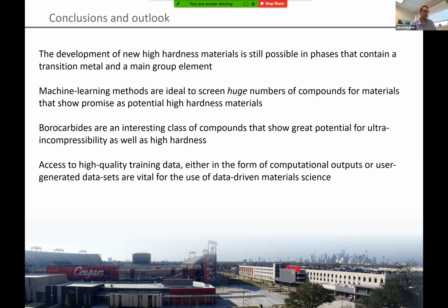Yeah, that's actually partly one of the ways that the field, in terms of what I talked about with the ultra hard materials, that's the way the people doing these diamond type materials have gone. So that's where there is certainly a huge amount of opportunity in terms of taking something like diamond and distributing nanocrystalline precipitates of diamond within the matrix, because there you start to artificially introduce or limit dislocation motion. Now this, I think, is coming more from a materials science perspective, controlling precipitate distribution at that point. We're looking at it from a standpoint of how do we simply identify these new materials.